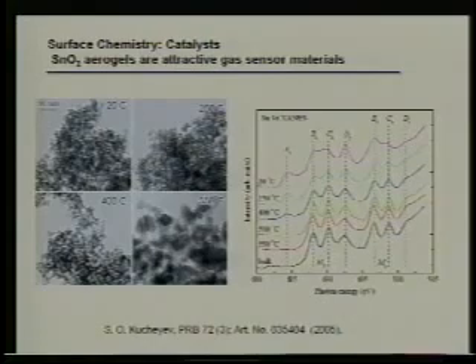And what we've now done is we've looked at the NEXAFS as a function of this. And we see that the near-edge structure is changing completely as we do our annealing. It turns out that at 20 degrees, the structure is akin to SnO, and it's amorphous. And if we map our amorphous SnO, it matches ideally with what we see at 20. But as soon as we start annealing, the material starts to crystallize and actually converts to SnO2. So here, just by annealing, we're actually changing the electronic structure of our aerogel. And this is actually very useful for catalytic purposes.